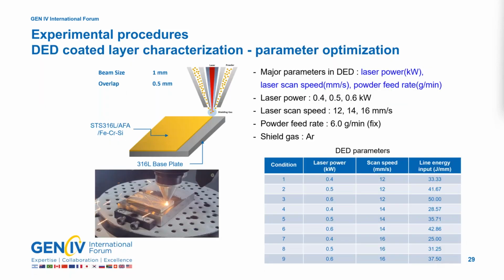Firstly, we performed DED parameter optimization for the combination of the newly designed DED equipment and the manufactured metal powders. Through preliminary experiment, we selected 9 conditions with laser power and laser scan speed as the main variables.